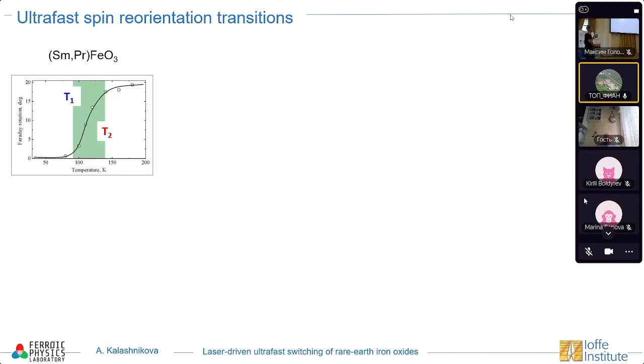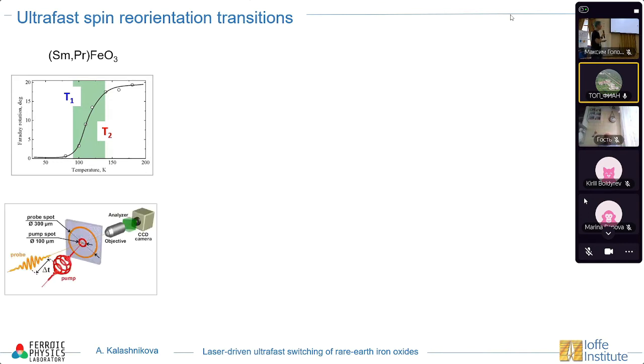So this is our material. It was grown by Anatoly Balbashov. This is samarium praseodymium orthoferrite. The choice of the material was mostly motivated by the fact that we wanted to have a large magneto-optical response, and this is a really very good material for that. So spin rotation transitions happen at, let's say, just above 90 K and at something like 130 K. This is our experiment. Basically, yesterday, Dr. Yusuf Foldi introduced the idea of the pump-probe experiments.